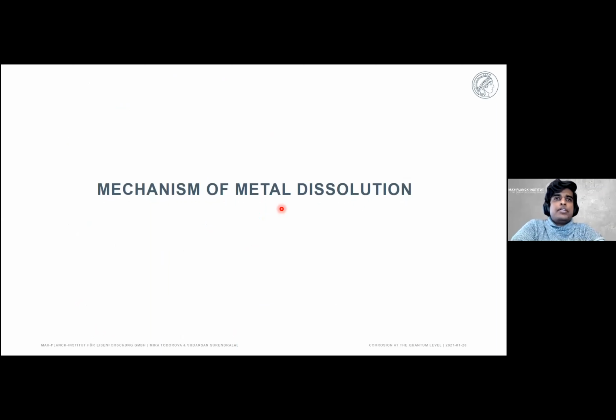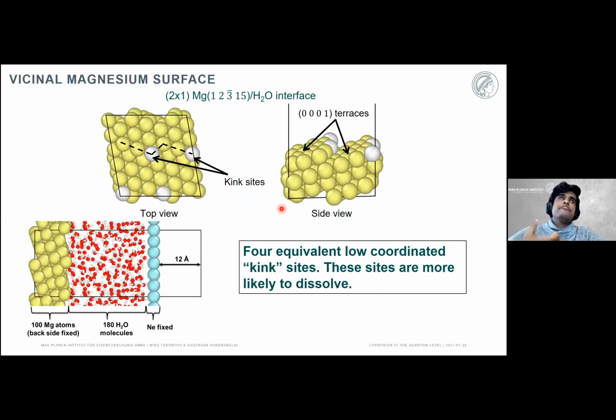The second application is to study the mechanism of metal dissolution, which is essentially the very first step of metal corrosion. In order to simulate this, we created what's known as a vicinal surface, not a clean, ideal 0001 surface, but rather a vicinal surface which has step atoms and kink atoms. These kink atoms that you see here that are highlighted in silver are usually atoms of the metal that have a lower coordination. It means that we expect them to be much more susceptible to dissolution.